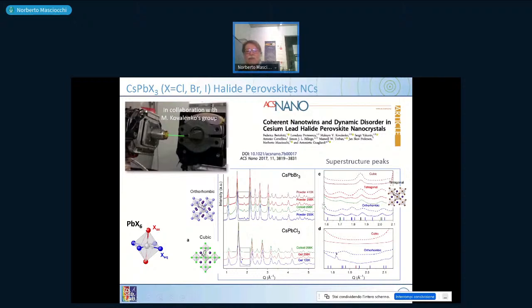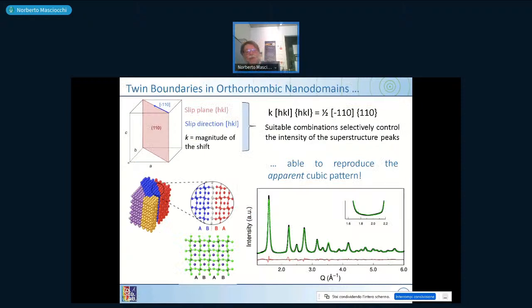Can we follow the transitions and interpret these changes by changing the temperature and conditions? So if you take now, we go to the end and we see the result. This plot is cesium lead bromide, which is simulated at high temperature using an orthorhombic system. The orthorhombic system had peaks in this area. Now they disappear. They disappear because we have taken the original orthorhombic structure, which is shown here, which is a sequence of A, B planes.